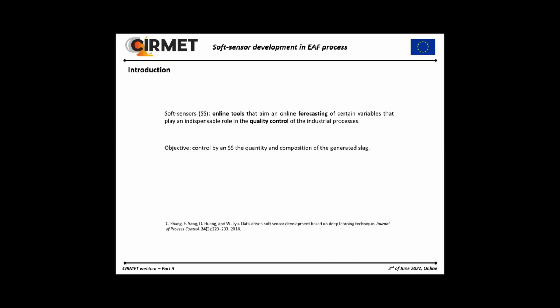The objective of this work was to control, by a soft sensor, the quantity and the composition of the generated slag in an EAF process. The amount of slag is a very important factor because it's an indicator of the efficiency of the process. So an estimation prior to the melting process is considered of great importance from an economic point of view.